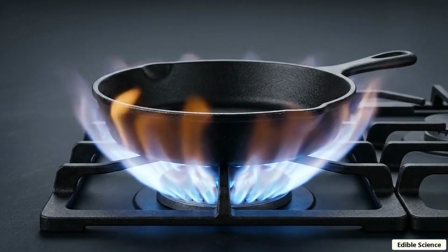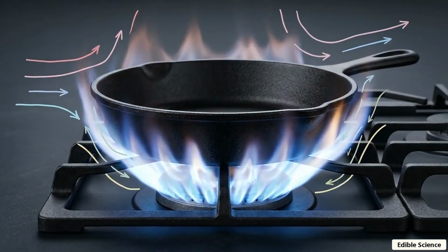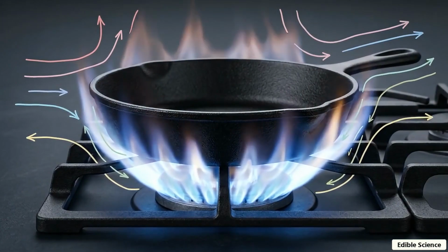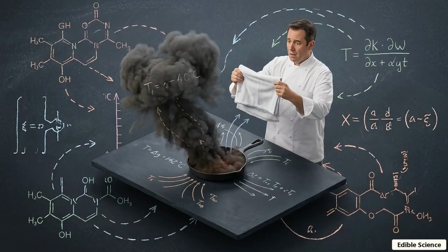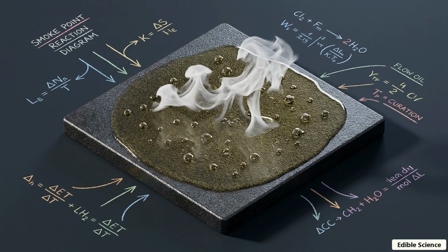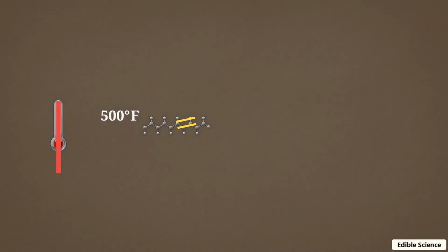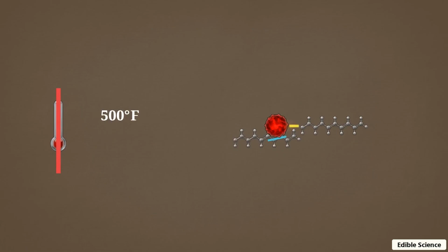Even with a high iodine value, the double bond hooks remain dormant until they receive enough activation energy to spring the trap. Professional kitchens generally teach that cooking oil should never be heated until it smokes. While smoking oil degrades the flavor of food, pushing the lipid past its smoke point is a thermodynamic requirement to initiate the solidifying reaction. As the temperature climbs toward 500 degrees Fahrenheit, the thermal energy becomes intense enough to crack those tense double bonds open. As the chain fuses, the broken bond leaves behind an unbalanced, desperate carbon atom called a free radical. It lunges at a neighboring fatty acid chain, fusing the 2 molecules into a single structure.